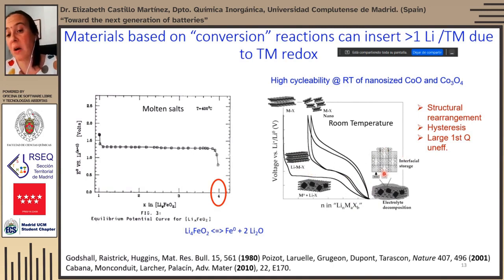And this has been assigned to some interfacial storage on the surface of the metallic nanoparticles, as well as to some possible further reactivity of the decomposition products. So although using these materials with huge gravimetric capacities would be very desirable, the large hysteresis and large first cycle Coulombic inefficiencies prevent them from going to market. Still, the mechanisms of reaction are still being explored.